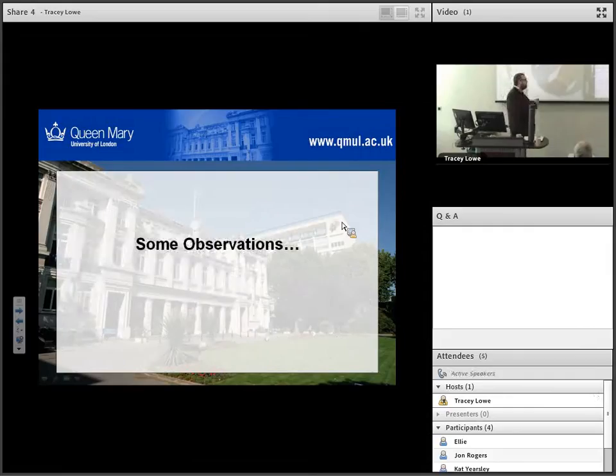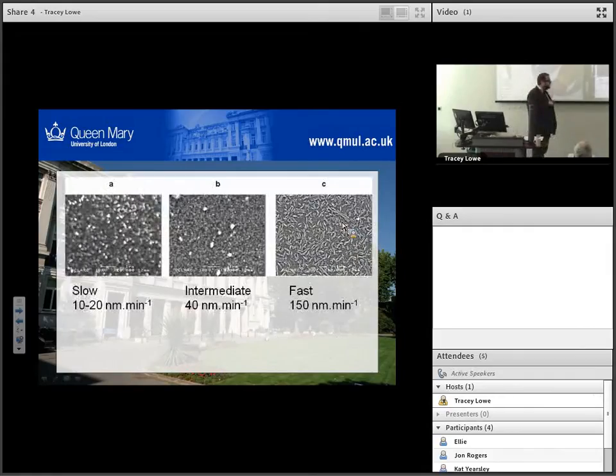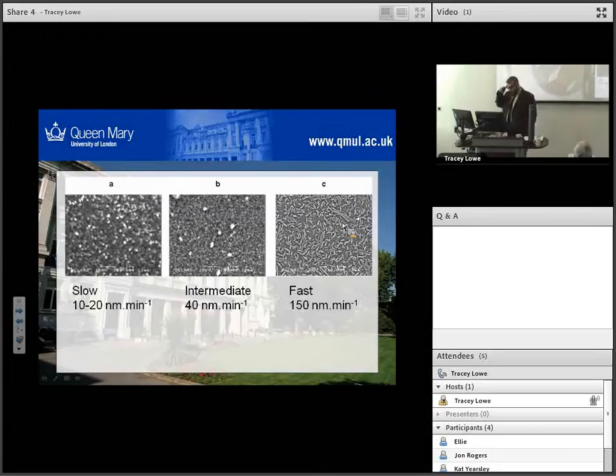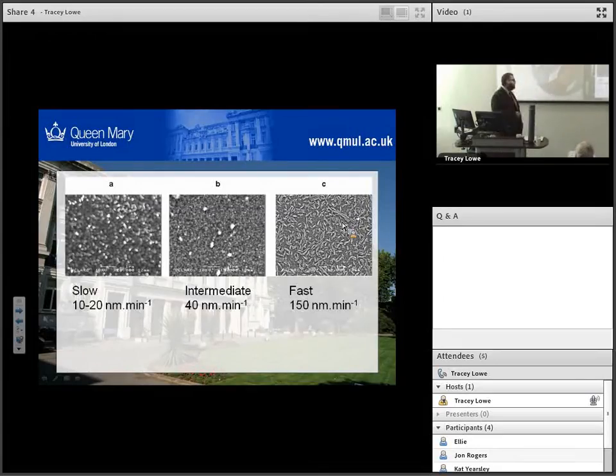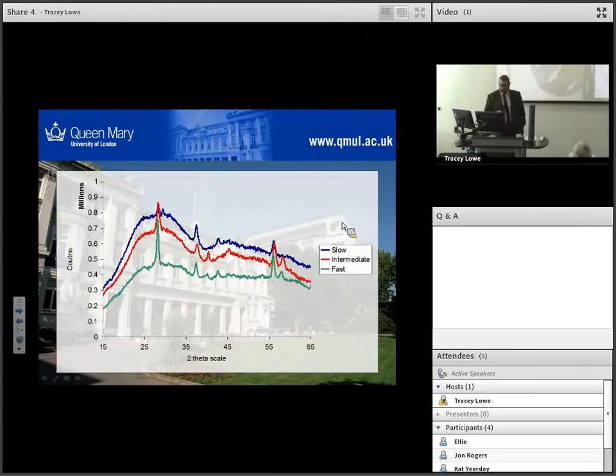But anyway, okay, so some observations. This is from work we did a while back, actually, when I was a postdoc. We grew some vanadium dioxide films, we changed the growth rate, and we can see some structural changes in our electron microscopy. Okay, we can also see some changes in our X-ray diffraction.